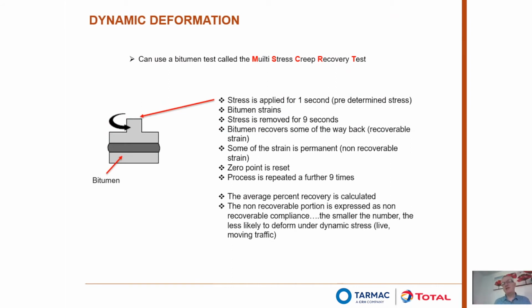We can talk about this MSCRT test, which is one of the European test methods, where you're effectively sticking together two plates with a little bit of bitumen, and with the top plate you're applying a 1 second predetermined stress to it, and that results in the lower plate moving as the bitumen strains. The stress is removed for 9 seconds, so it allows a little bit of recovery, and then it's repeated a further 9 times, so a total of 10 actions. And what we're measuring on this is the amount of recovery that we get back from that stress that's been applied, and it's averaged over those 10 periods.